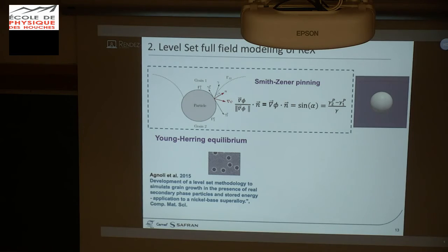And it's exactly what you can see in the first simulation, where you have an interaction of a 3D grain interface with the second phase particle, and you can see the pinning effect of the static particle on the grain interface. And here you have the same thing with the level set simulation in 2D, where you can see the grain interface in green. The interaction is complex, because at the beginning you dilate the grain interface, which is energetically favorable, but at the end you create interface. Finally, the Smith-Zener pinning pressure is exactly defined by the fact of creating or dilating some grain interface at a position of interaction with a second phase particle.